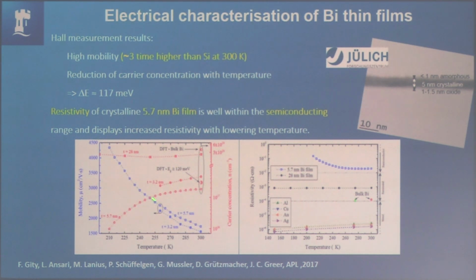The electron mobilities that we measure are about 3 times higher than silicon at room temperature. And that's large silicon. When you get down to these very small lengths, you have a lot of different surface scattering. You have all kinds of effects that kill your mobility. So that you can do that in these very thin films is a big deal, because the industry paid, I don't know, hundreds of millions of dollars just to strain silicon to get incremental changes in the mobility. So to say that we can improve it by a factor of 3, people start to get excited. Of course, we haven't manufactured anything yet.